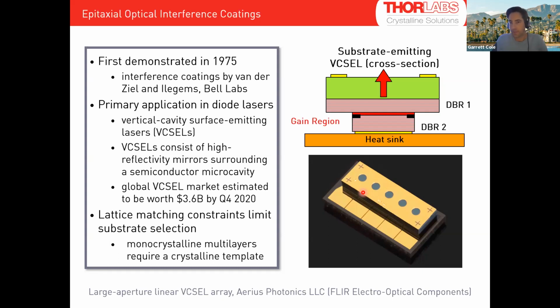So obviously, these single crystal interference coatings have found a lot of nice uses in integrated optoelectronics, but you don't see them in general optics applications. And the major limitation is the fact that it's a single crystal structure, which requires crystal growth, and so you have very severe constraints on substrate selection. You need to meet the so-called lattice matching condition, which means your interatomic spacing and crystalline symmetry needs to be the same. So you can't choose an arbitrary substrate. Obviously, you can't choose a glass to deposit on.